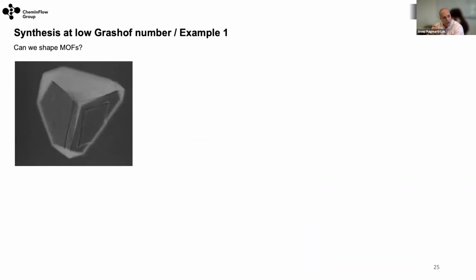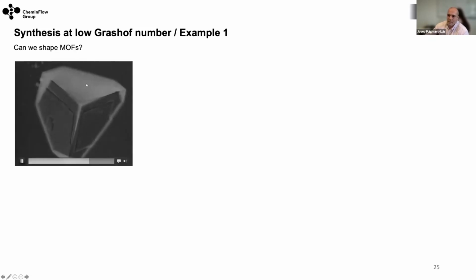So, the question here is, what can we achieve when we have a low Grashof number? Well, if we look at this crystal that is growing, we see that we cannot control where the crystal grows, it just grows. We have a polyhedral shape, based on the crystallographic information that this material has. But there are some processes ongoing very close to the crystal growth. There are some depletion zones, and some convections being generated while the crystal grows. So if we are able to achieve a low Grashof number, some of these processes will be reduced. And the idea of our research is, what will be the effect of these low Grashof numbers on crystal growth?